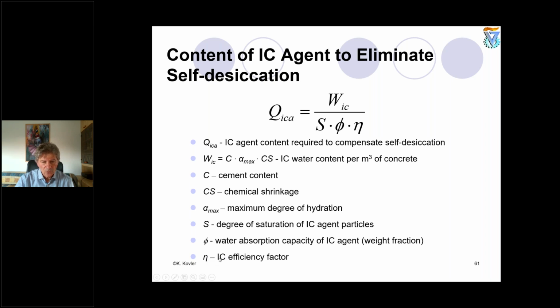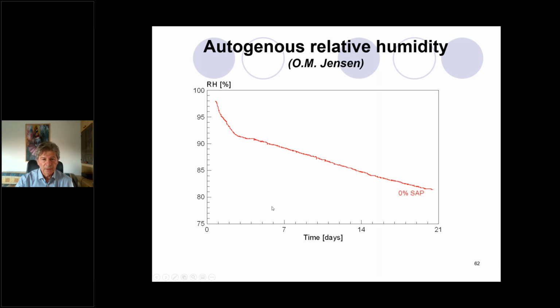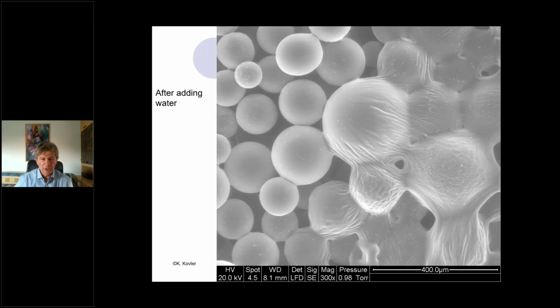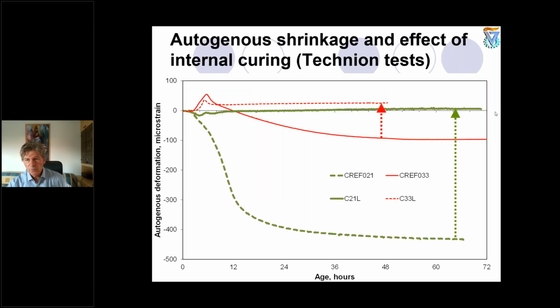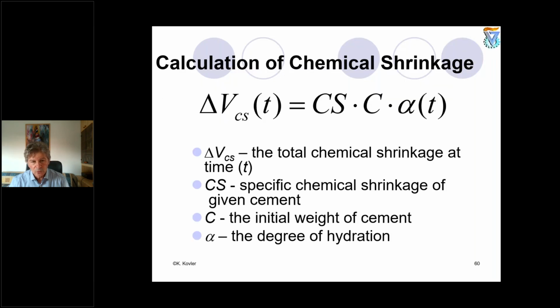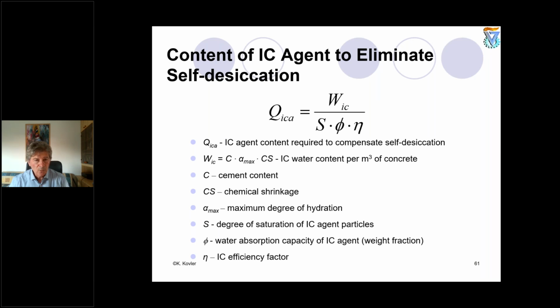And ETA, which is also a very important issue, is called the internal curing efficiency factor. How to understand what the efficiency factor is? I will explain later on. But in principle, if I come back to the diagram of autogeneous shrinkage, you can see this is a ratio between the deformations. I'm speaking about the plateau. If we completely eliminate autogeneous shrinkage, the efficiency is considered 100%. If we eliminate 50% of the autogeneous shrinkage, the efficiency factor is equal to 50%. This is very simple to understand, and we know how to introduce this efficiency factor in the formula. And then we have everything to calculate precisely how much of this or that internal curing agent should be added.